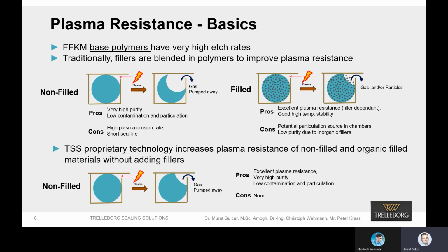So when we talk about the filled material, the similar scenario, if the O-ring is in the groove and the plasma strikes, as I mentioned in the previous slide, the filler particles shield the polymer backbone from the plasma exposure, and therefore the etch rate is lower than the non-filled case. But there's a little bit of difference here, because when the non-filled material is etched away, the etched products are usually very small fluoromolecules, and therefore they can be pumped away and they don't contribute to particulation. That's why non-filled materials really provide a very pure system.